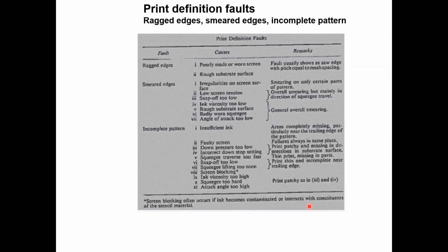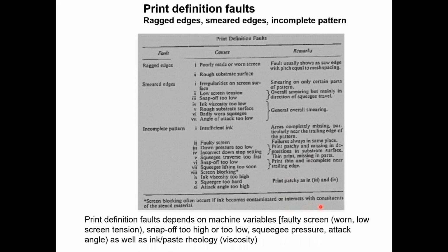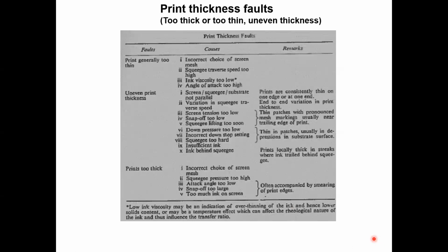There are all kinds of defects and faults that you can create during screen printing, and I'm not going to go through the details. I copied this from the source that I gave you on page number 1, references. But the print definition faults depend on machine variables, like faulty screening, or snap-off distance between the substrate and the screen being too high or too low, squeegee pressure, attack angle, at what angle the squeegee will come and strain the ink, and also the ink or paste rheology, viscosity.